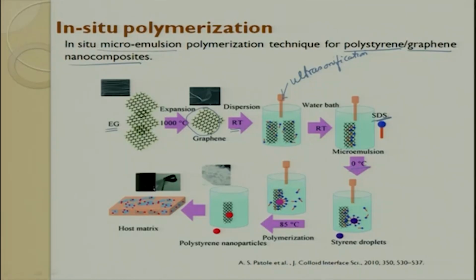Then at 0 degree Celsius, we try to add styrene droplets, because what you want is polystyrene. So styrene droplets are added. Then at 85 degrees Celsius, you again sonicate, and you see that these polystyrene particles are formed, and this SDS is also added, so they try to mix with each other properly and get whatever is the output.